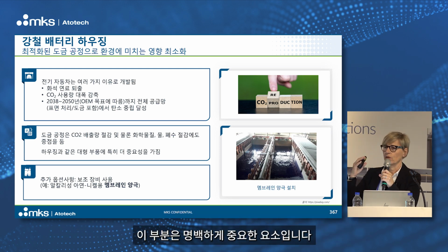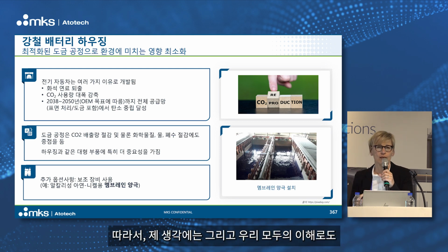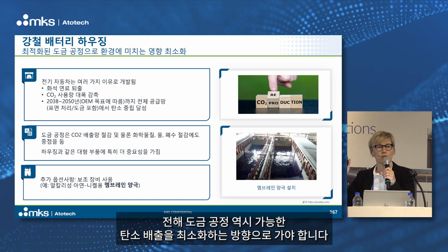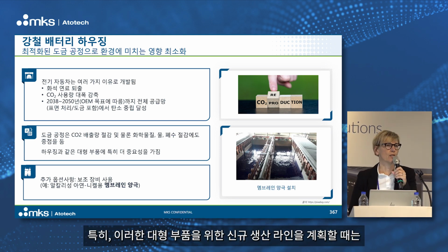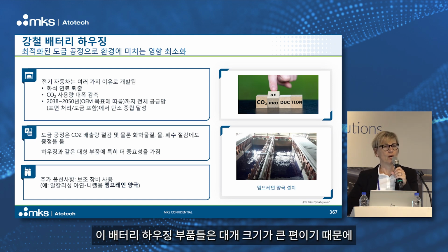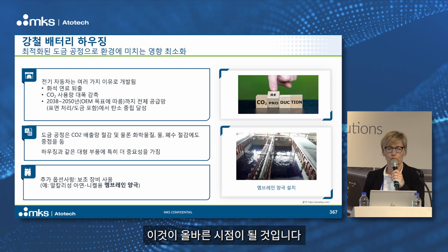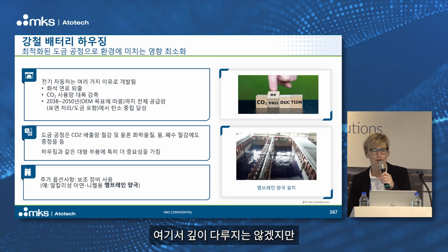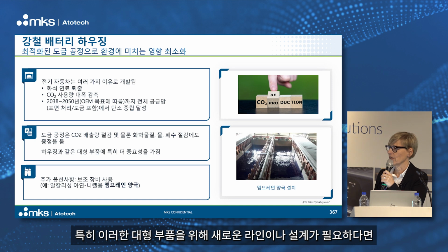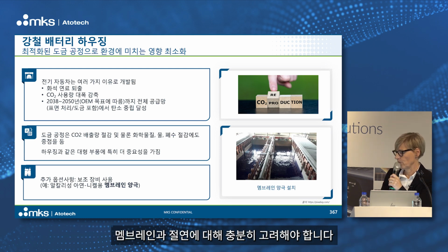And it's clear that, especially in that case, for my understanding, for all our understanding, the electrolytic plating process should really be as CO2 friendly as possible. And therefore I believe, especially when there is a new line for these huge parts, because normally these housing parts are also large direct parts, this is the right moment to think about membrane anodes. We discussed that this morning, so I don't want to go in depth there, but especially if new lines or new designs are needed for these large parts, membrane anode installation should really be thought over.